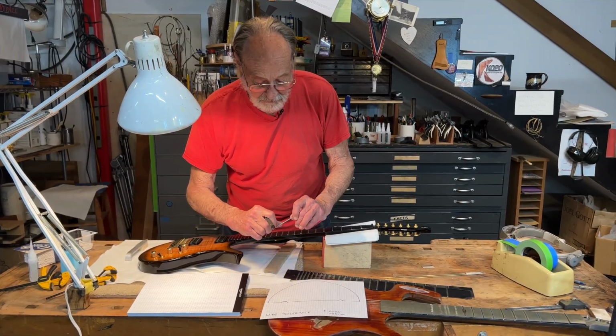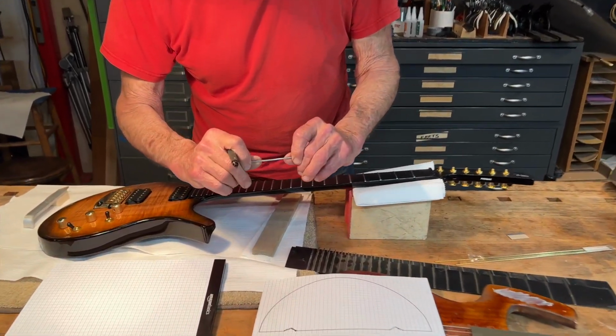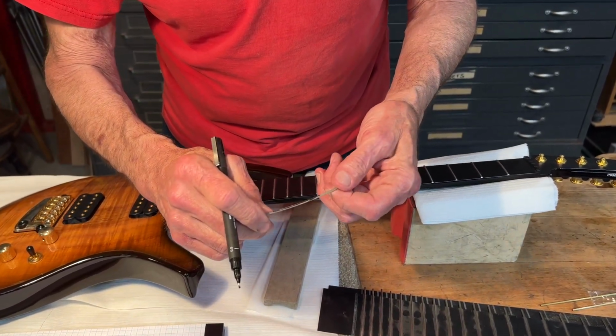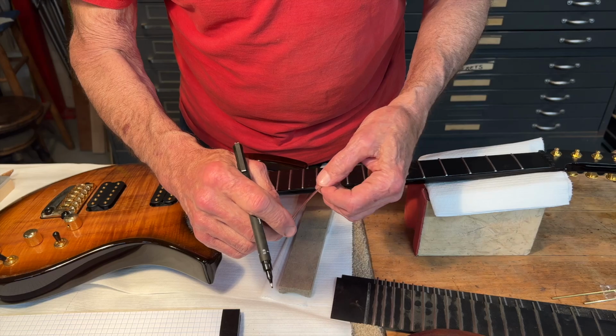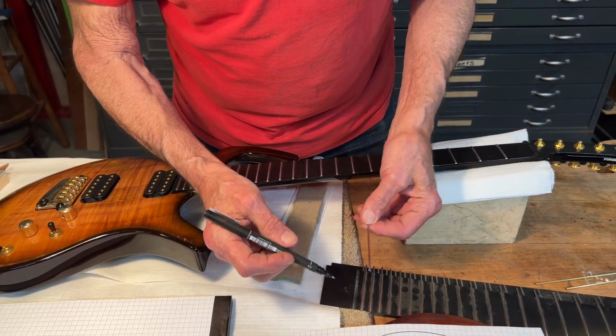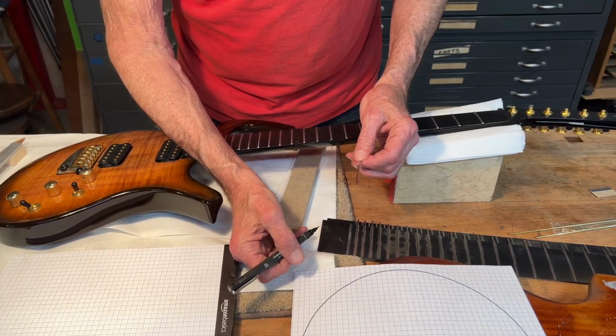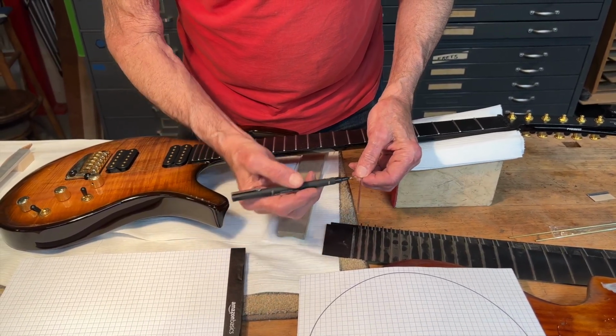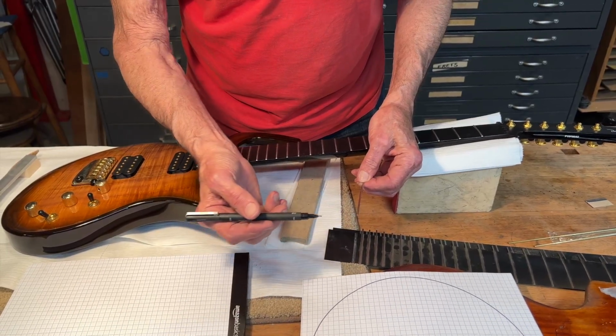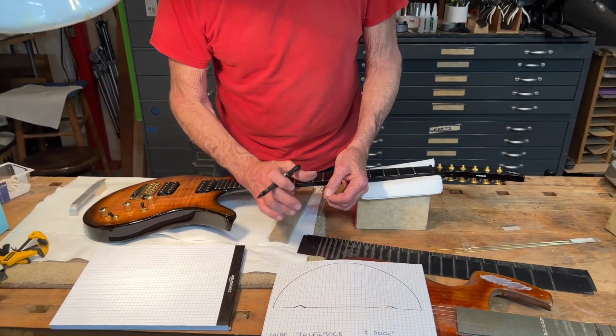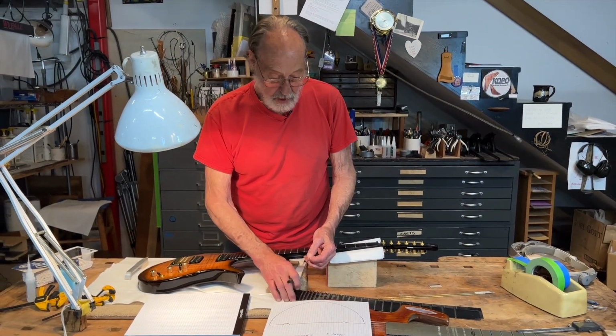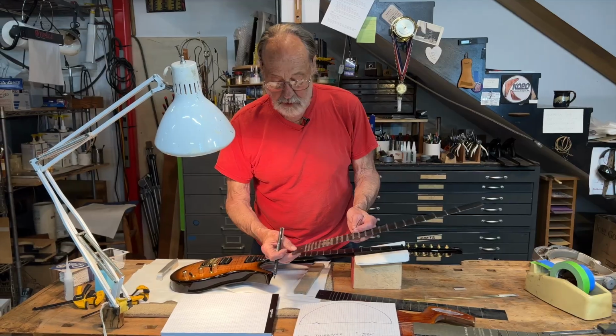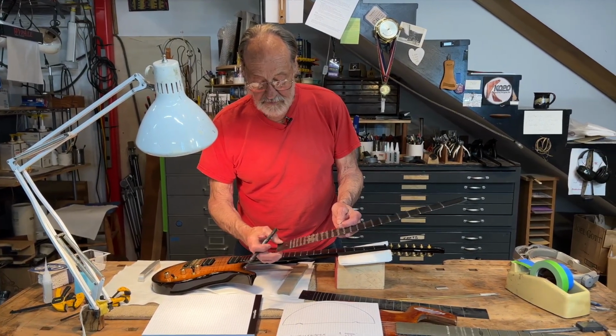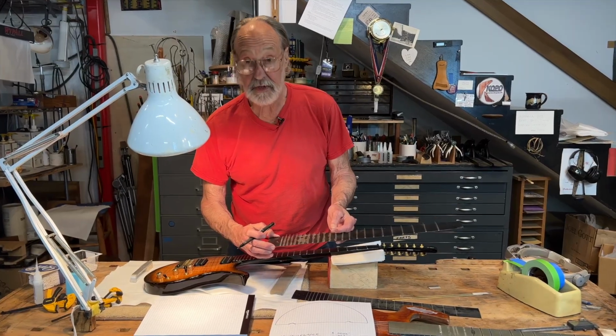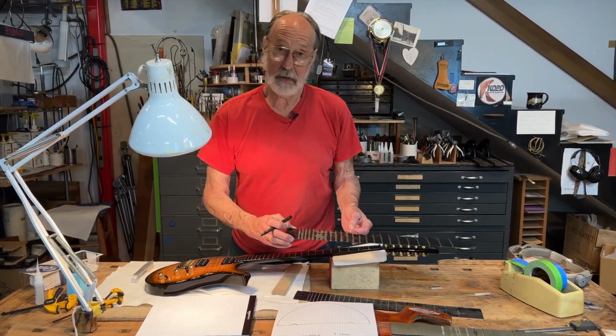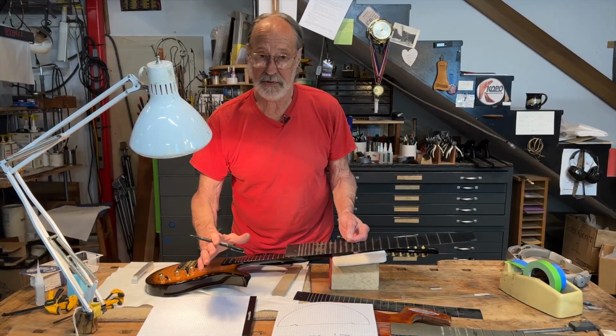Let me tell you a little bit more about this fret wire thing. So first of all, we searched and searched for an adhesive that was going to be appropriate for gluing stainless steel wire to composite material. Now, the challenge is that the stainless steel wire has a significant thermal coefficient. In other words, it changes size in response to changes in temperature. Whereas this high temperature epoxy resin, fiberglass, and carbon fiber structure that is the fingerboard has near zero thermal coefficient. It doesn't care what temperature it is, it just holds still.